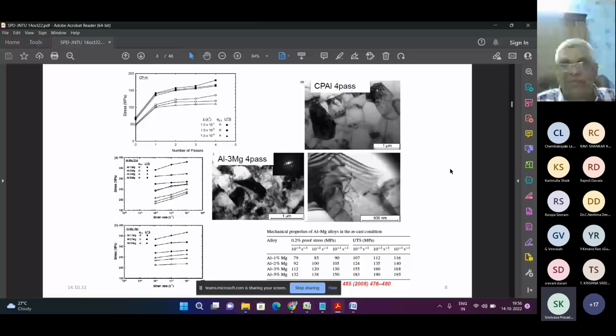So here, when we are working on aluminum magnesium alloys, what we have done is we go on increasing the magnesium content, 1%, 2%, 3%, 4%, 5%. Go on adding the magnesium and see how the mechanical properties are changing. And what we have found is after 4% magnesium, there won't be much change. Why? Because the precipitates that are forming, Mg2Si or Al3Mg2 precipitates, don't have much influence on the mechanical properties at 4% or 5% magnesium content. So most of the people restrict this to aluminum with 4.5% magnesium content only.